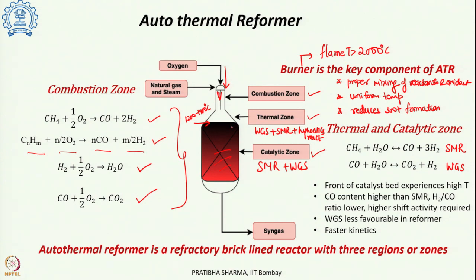However, as we go down across the bed, the temperature will decrease, because in the catalytic bed the steam methane reforming reaction will occur, which is an endothermic reaction. And towards the end, the temperature of the syngas will be lower, somewhere between 700 to 1050 degrees centigrade. So in the catalyst bed, the top temperature is higher, towards the end of the catalyst bed the temperature is lower. So a high temperature gradient is experienced by the catalyst bed.